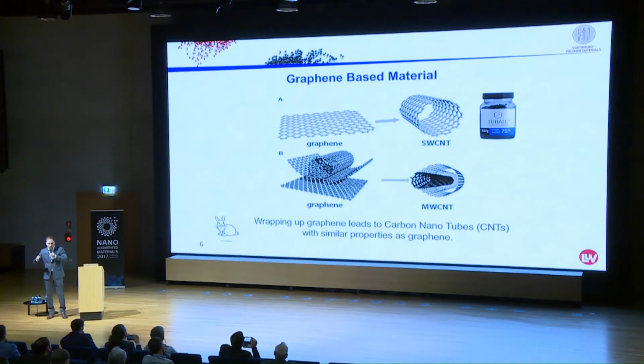And we can imagine, out of graphene, other nanostructures like carbon nanotubes. If we have a single layer of graphene and we wrap it up, it leads us to a single-walled carbon nanotube. If we have several layers of graphene, called multi-layer graphene, and we wrap it up, we get a multi-walled carbon nanotube. What is a bit counterintuitive here is that the fewer layers you have, the better the performance is. So the best material you can get is a single-layer graphene or a single-walled carbon nanotube, such as TUBALLs here. And I can tell you, I worked with all this material, with graphene, multi-layer graphene, multi-walled carbon nanotubes from different suppliers, but also with TUBALLs, and I get really the best results out of TUBALLs, so it's outstanding here.